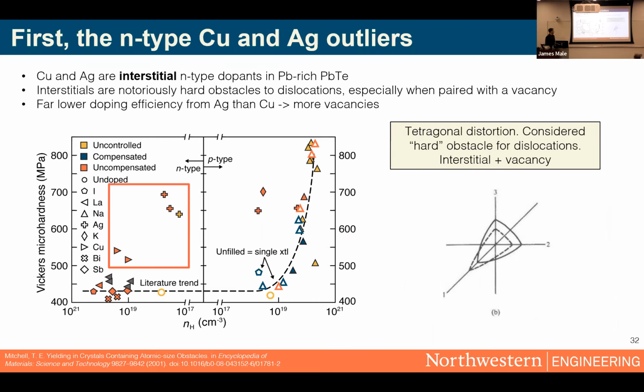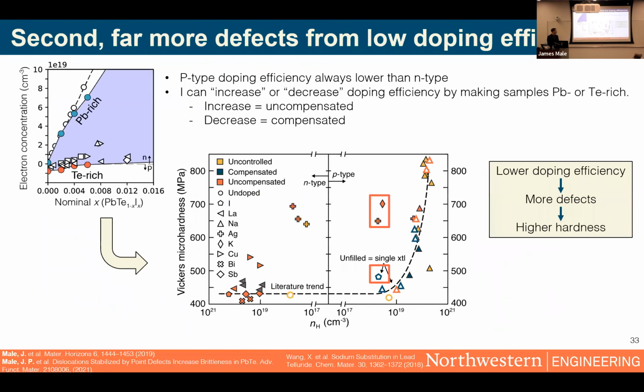These copper and silver dopants are unique N-type dopants in that they sit on the interstitial site. And it's kind of a textbook idea that interstitials in a rock salt lattice can create a very unfavorable strain distortion for a dislocation to move through. So they're very resistant to plastic deformation. And also notably, we broke that trend of low hardness in N-type materials. So obviously we should be looking at this sort of dislocation defect interaction rather than the carrier concentrations.